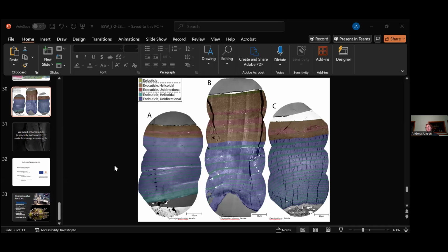So if I start bending that, it's going to warp out of plane, right? If I try to bend it down, it's going to warp out of plane in the other direction. It's very difficult to predict how those types of laminates will behave, but insects use them all the time. There have been a couple of instances where engineers have tried to take advantage of out of plane effects with asymmetric laminates.